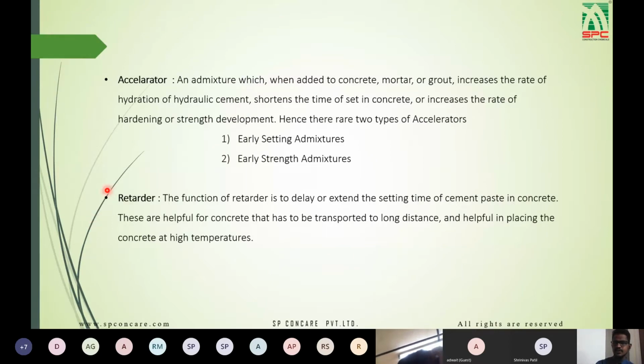Retarder acts in the opposite way of an accelerator. Where an accelerator reduces the setting time of concrete, a retarder delays the setting time of concrete. So the function of a retarder is to delay the setting time of cement paste in concrete. Mostly these are helpful for concrete that has to be transported over long distances, or helpful in placing the concrete in higher temperatures. Long distance means mostly RMCs. The retarder is mostly used in RMCs.